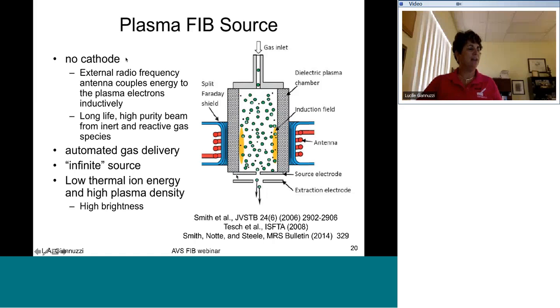the plasma source is basically, it has no cathode. It uses an external radio frequency antenna, which couples energy to the plasma electrons inductively. This yields a very long life, high purity beam from inert and reactive gas species. So typically, actually, xenon is pretty expensive. It comes in bottles that are only about this big, but if you have a bottle of xenon that's about this big, it will last you your lifetime and probably the lifetime of your children and grandchildren. So you don't need a lot of gas at all for this source. So that's a good thing.